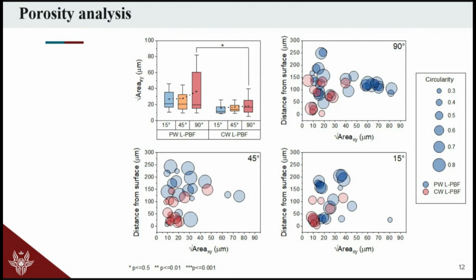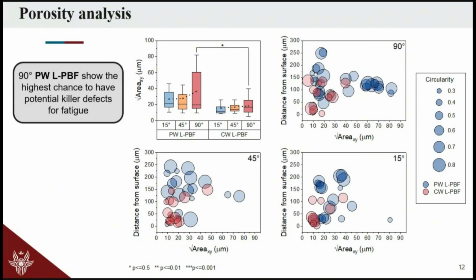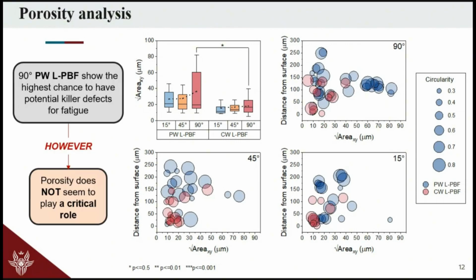near the change in between the contour and the bulk part of the strut. This would suggest, preliminary, that this might be the driving mechanism. But if you remember the graphs before, basically it's flipped, because the pulsed wave laser powder bed fusion reports a higher fatigue strength with respect to the continuous wave. So again, probably this is not the mechanism.